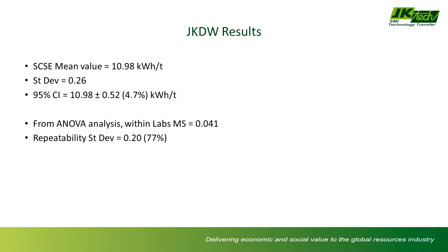I'm quite happy to say plus or minus 5% on the SCSE value. I'm also quite happy because the SCSE also relates back to the SG. So we're not only looking at the variability in the breakage, we're looking at some of the variability from the SG measurements, and even combined, we're getting this down to plus or minus 5%.